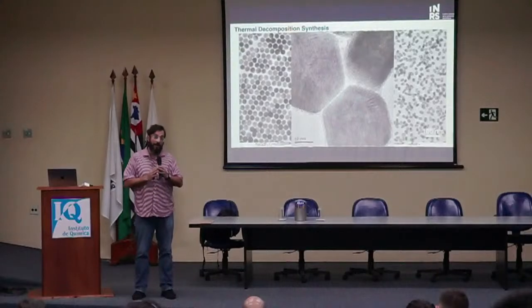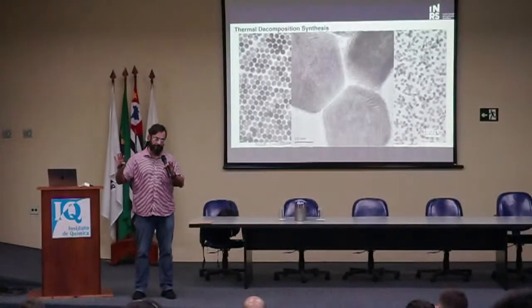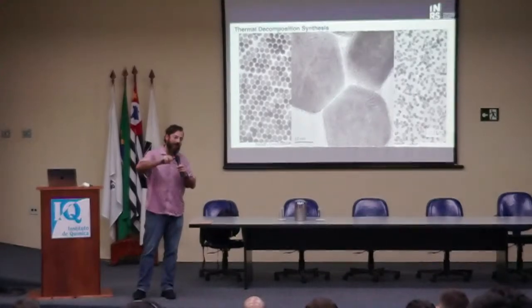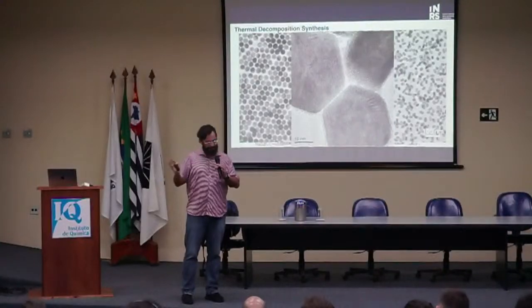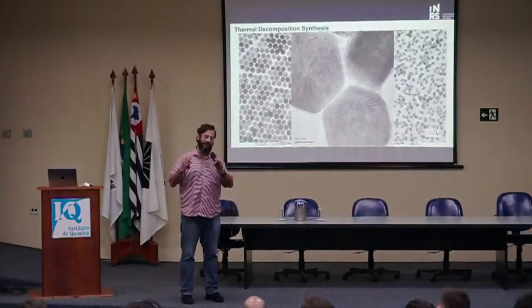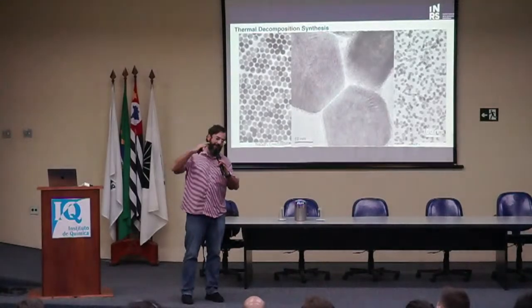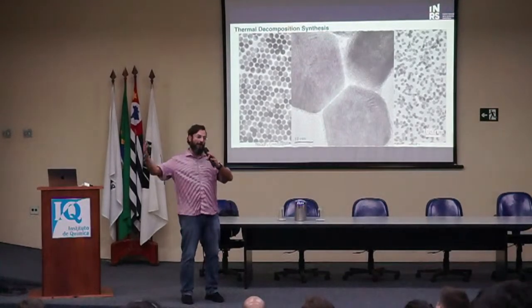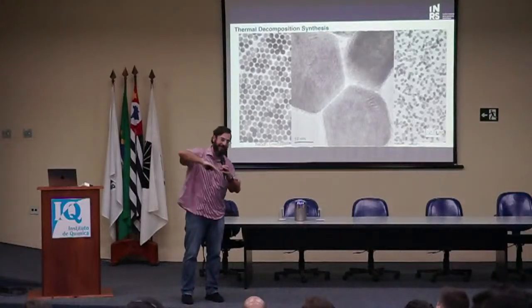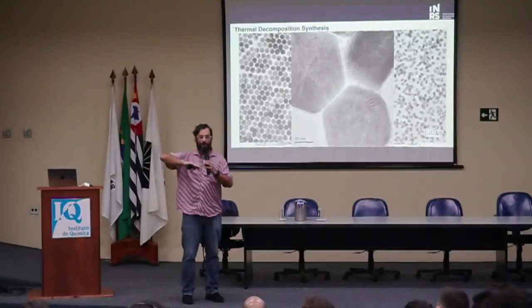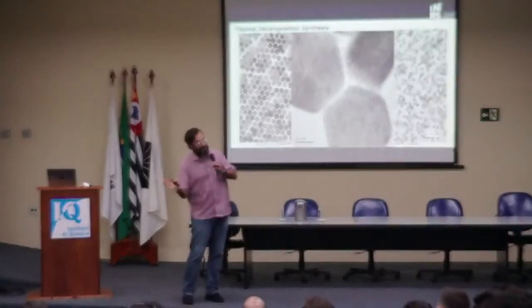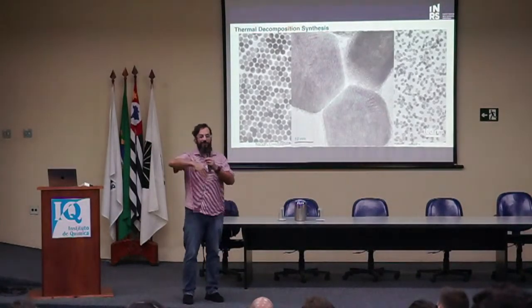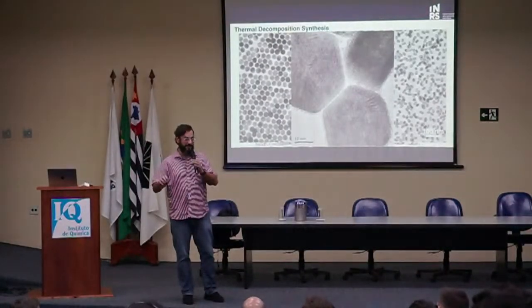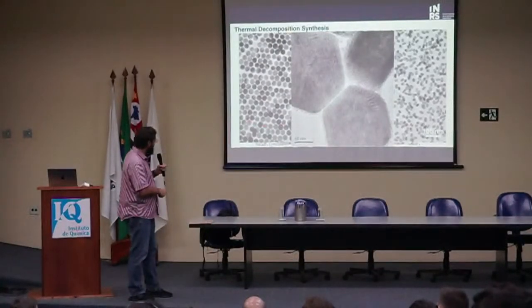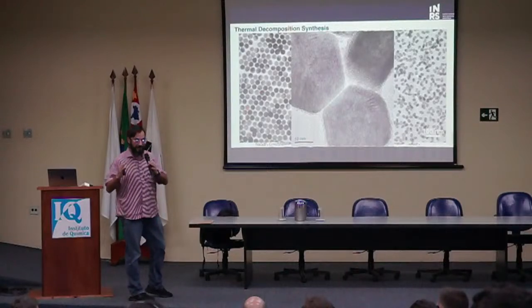And for applications in biology, especially in vivo, this is critical, because different size nanoparticles will behave differently in the body. And so, when you're working with living specimens, there's so many variables, and if you have a wide particle size distribution, you have big particles that will clear from the body using one mechanism, or go into the cells using one mechanism, and smaller particles will clear differently or use another mechanism to get into the cells, so it becomes a mess. So when working in vivo, just as a suggestion, you want to make sure you have a very tight particle size distribution.